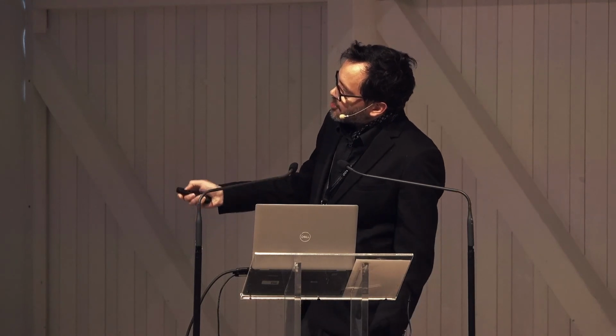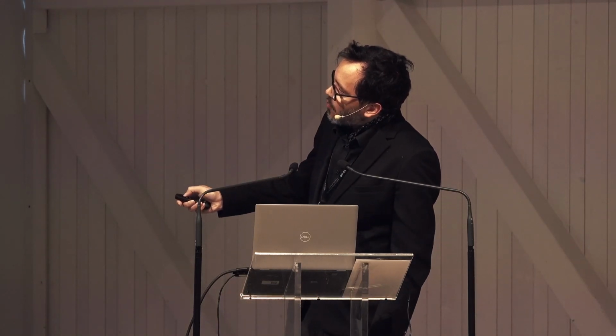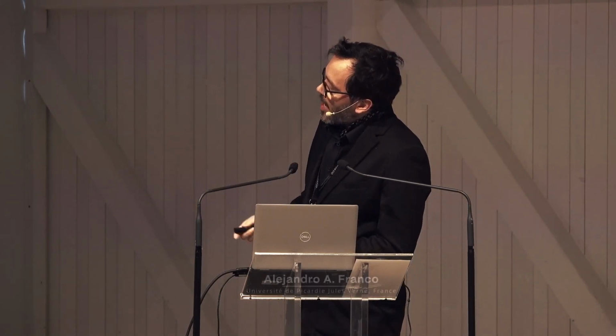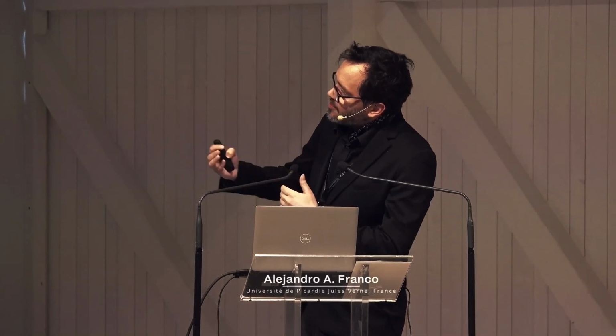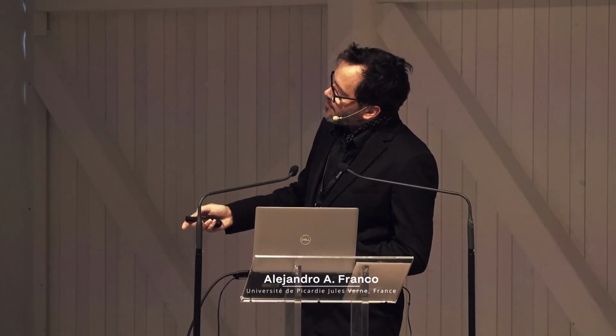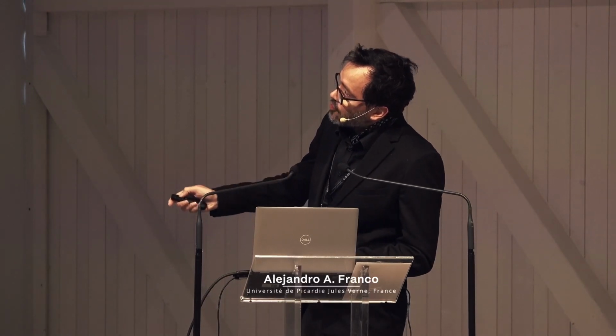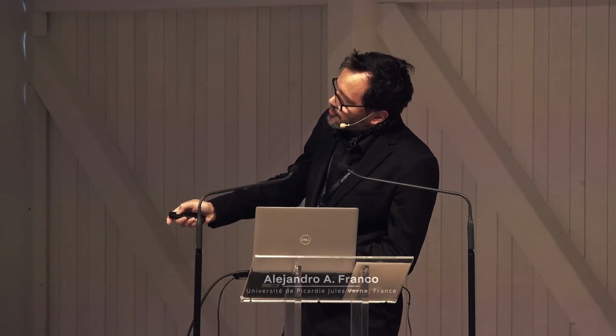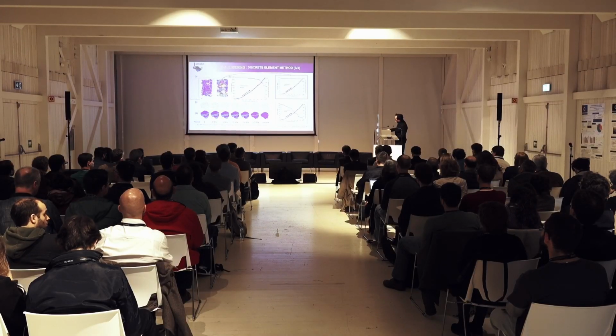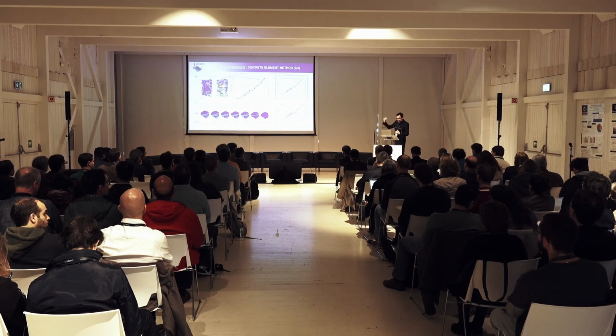Right? Cracks are here represented in light blue. And along the calendering process, you can even actually track what is going to happen in each individual active material particle. Here you see along the compression for the calendering how the number of bonds between the primary particles are disappearing, so are being destroyed. And you can actually, with this model, even identify differences in terms of degree of cracking for the active material particles which are closer to the calendering roll and the ones which are closer to the current collector. Okay? And basically we found that the particles which are closer to the current collector will crack more than the particles which are closer to the calendering roll.